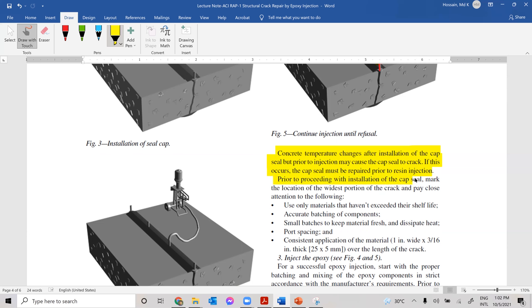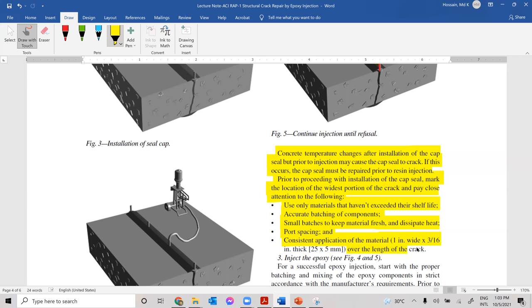When selecting the cap seal material, consider: non-sag consistency, moisture tolerance, working life, and rigidity — meaning modulus of elasticity. Concrete temperature changes after cap seal installation but prior to injection may cause the cap seal to crack; if this occurs, the cap seal must be repaired before injection. Prior to cap seal installation, mark the location of the widest portion of the crack. Use only materials that have not exceeded their shelf life, use accurate batching with small batches to keep material fresh, and apply material consistently over the length of the crack.